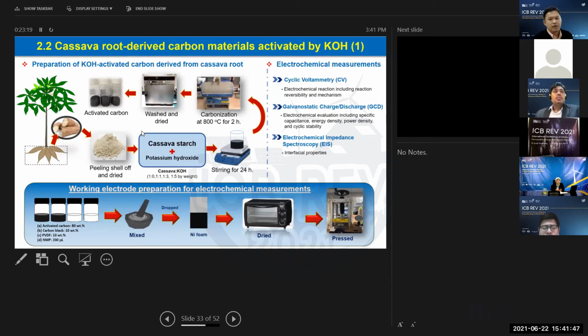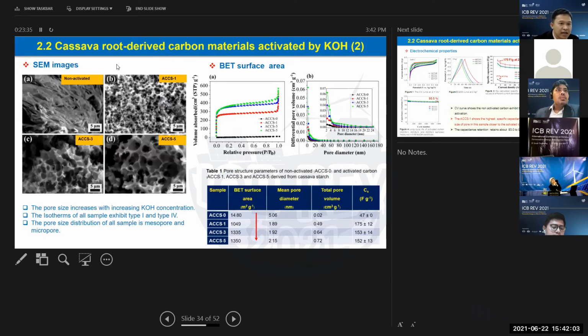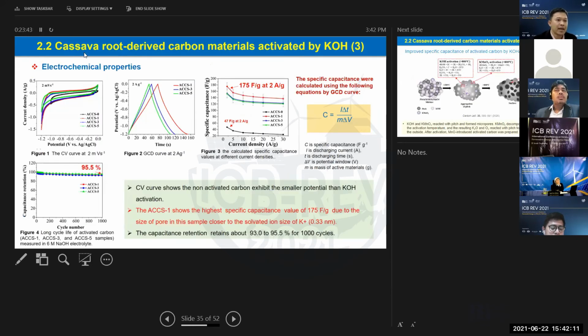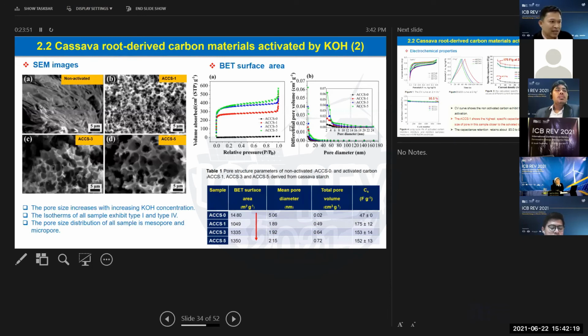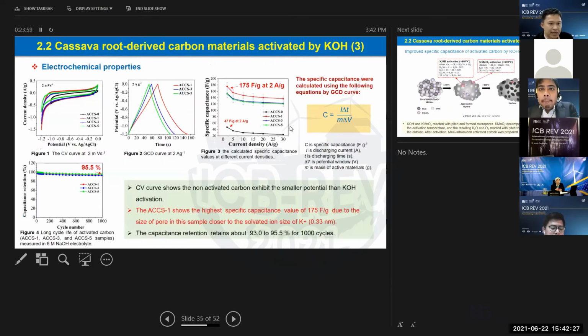And for the second work, as I mentioned, we try to use potassium hydroxide as the activating agent. And for the process, we also do the same for the preparation of the carbon. And these are the SEM images of the samples we prepared. And we study the electrochemical properties. But this time, as you can see from the SEM image, you can guess that the pores are quite small, even smaller than in the previous work. So we expect that we would get better electrochemical performance. And as expected, we can obtain a high specific capacitance up to 175 farad per gram at 2 ampere per gram.